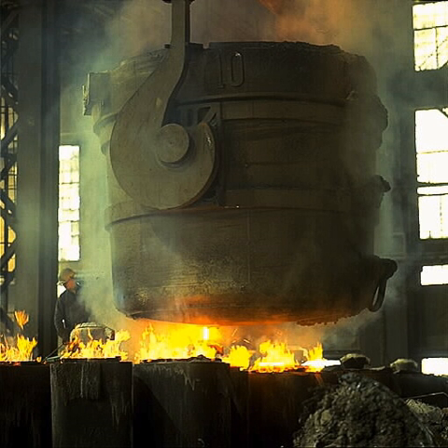High chromium white iron alloys allow massive castings, for example, a 10-ton impeller, to be sand cast, as the chromium reduces the cooling rate required to produce carbides through the greater thicknesses of material. Chromium also produces carbides with impressive abrasion resistance.